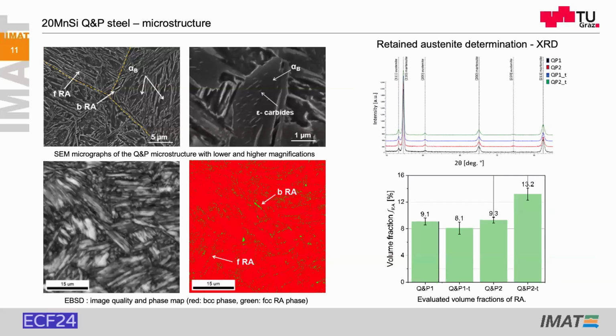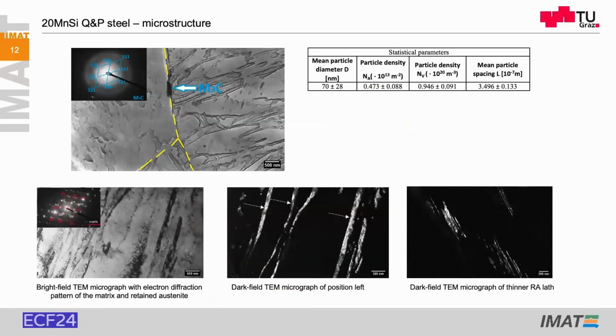The microstructure is quite complex. It is a martensitic matrix. We have retained austenite in blocks. Excuse me that I cannot show it. A block here, retained austenite, and film retained austenite, evaluated with XRD. Yeah, also we were surprised that the retained austenite is 10% or more, due to the very thin filmy retained austenite films.